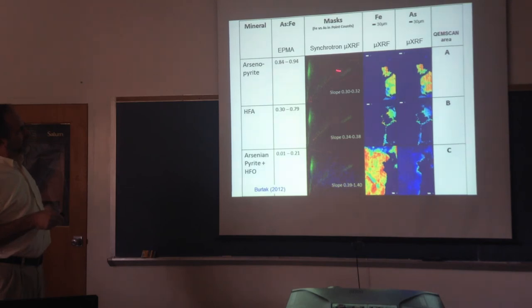We can learn that the ratio of arsenic to iron based on electron microprobe is around 0.84 to 0.94, and that's basically almost 1-to-1 arsenic to iron, and that represents arsenopyrite, and that mapped out into these areas that we knew were arsenopyrite from QEM scan and optical microscopy.